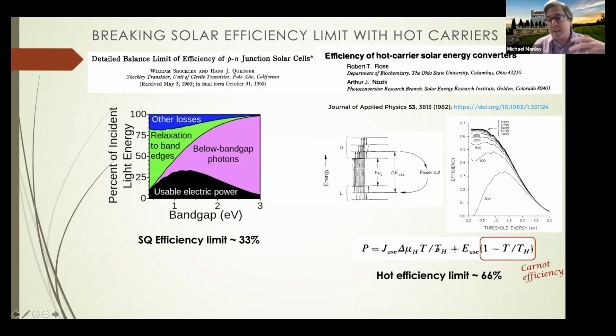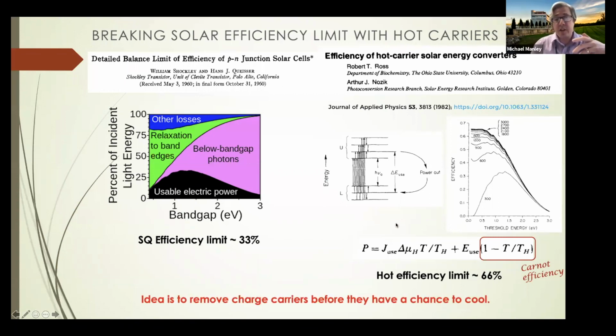That's a Carnot efficiency, because essentially you have a sort of internal heat engine, and then you've recovered a lot of that. But you can't recover all of it, of course, because you still have to pay Carnot. But the idea is, if you can pull the heat off, if you can pull them out higher, you're going to get a much higher Carnot efficiency. And this plot here on the right shows that as a function of hot carrier temperature. So as you push the hot carrier temperature up and up, you get more and more efficient conversion. But the challenge is to get those hot carriers out before they cool.